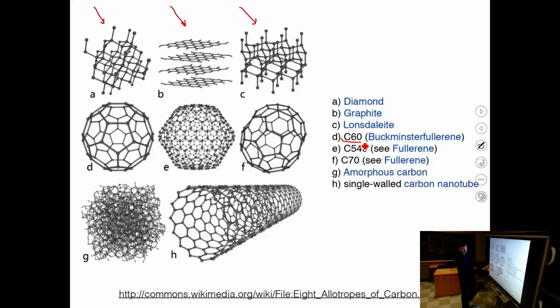Carbon nanotube, we're going to describe in great detail. It's essentially one of these layers rolled up. You can generate carbon nanotubes in many different ways, like an arc discharge, or a catalyzed growth where you flow methane, which has carbon atoms in it, at high temperature over a metallic catalyst, and methane decomposes, produces a carbon nanotube, hydrogen goes away, and the carbon nanotube grows from a metal like a nickel particle.